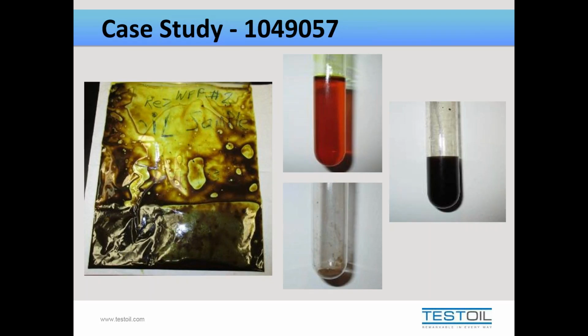So going back to this case study now, in the organic portion, we actually found many different types of chemistries. We found water. There was a lot of water; water was kind of everywhere here. Carboxylic acid and ester. And these types of materials, the carboxylic acid and ester, are typically attributed to the formation of varnish in the system or degradation of the lubricant itself. And then we also found thermal oxidative compounds, which to us means that there were elevated temperatures in the system at the time, or overheating. So, typical products of lubricant degradation due to oxidation in the presence of water. Nothing too exciting going on there.